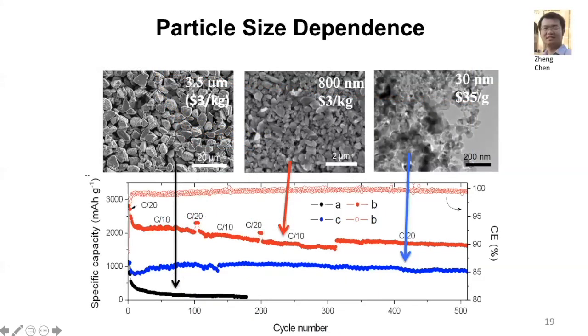And then we subsequently studied different kinds of particle sizes, because previously people tried to solve this problem by using silicon nanoparticles. When the particle is small, even though it undergoes the same volume expansion, when the size is in the nanometer range, the fracture mechanics completely changes, and they become less likely to fracture. But the problem is nanoparticles are very, very expensive. They are more challenging to make. So this is the typical price.